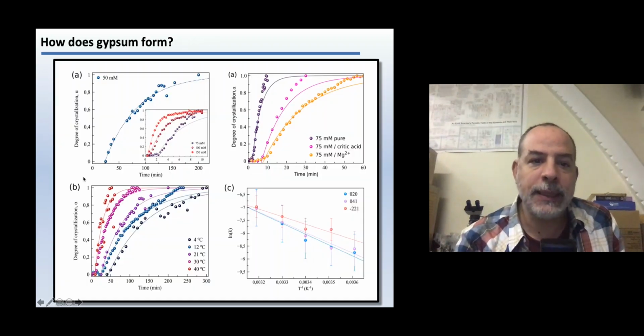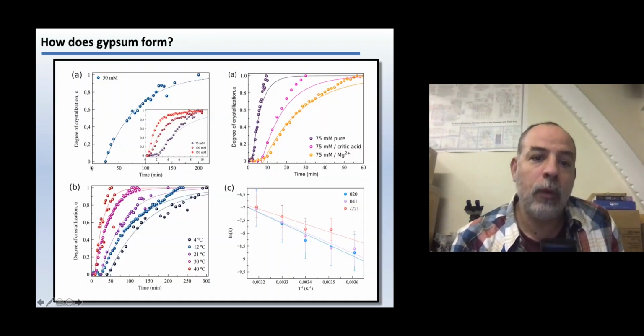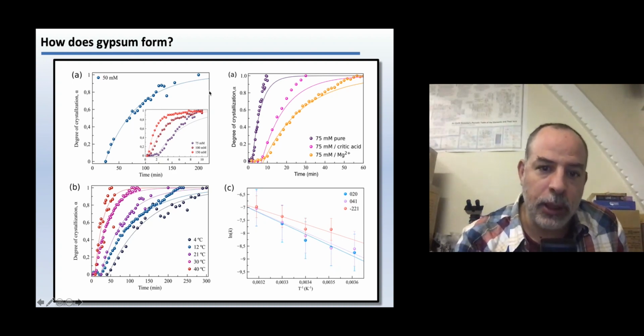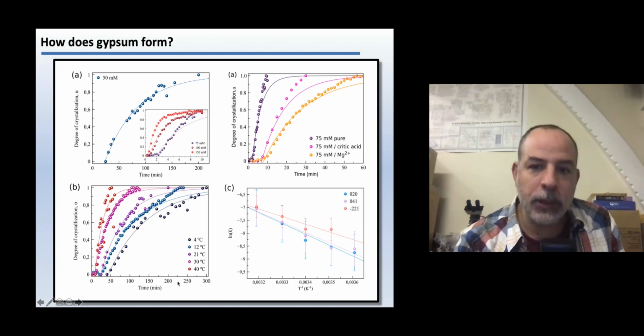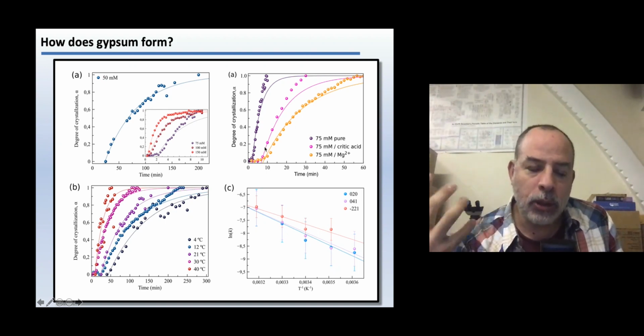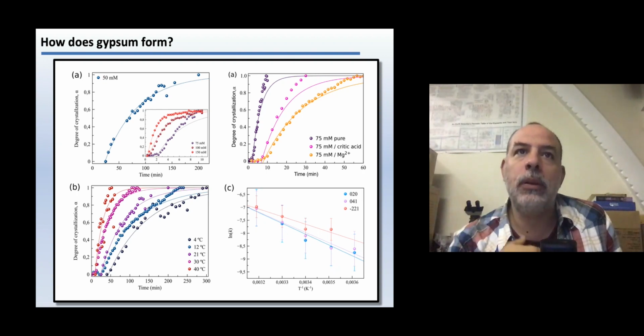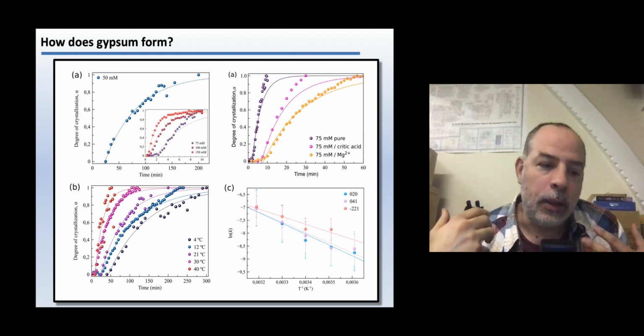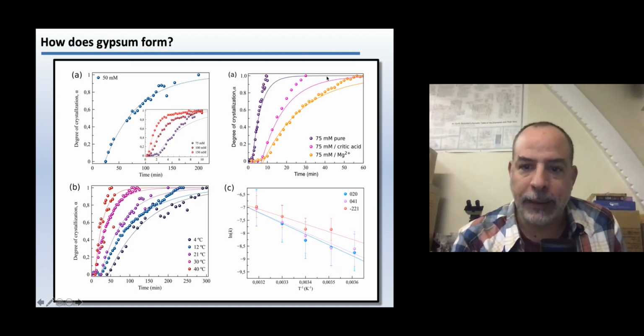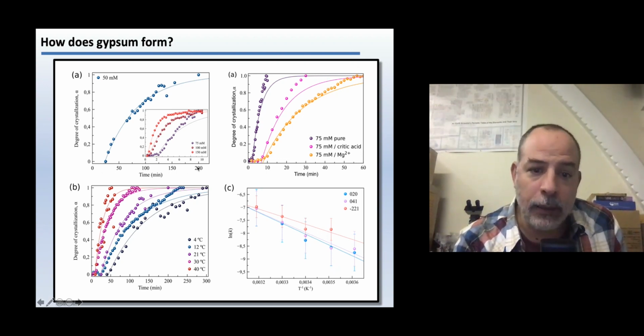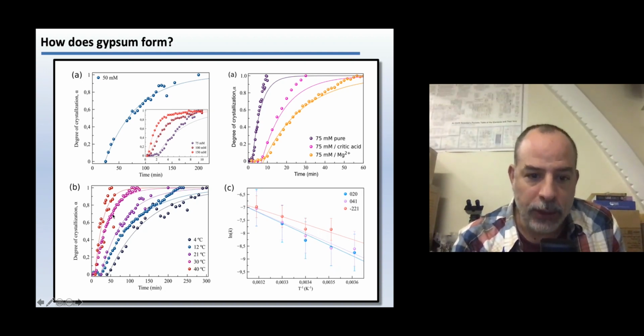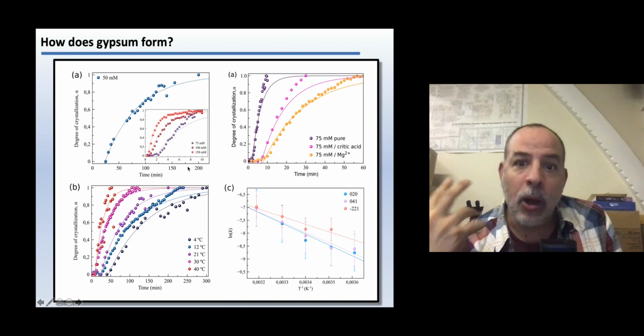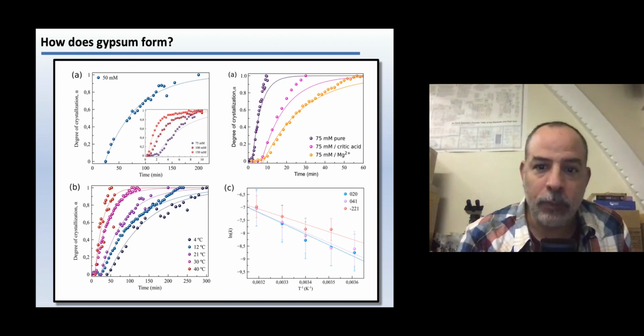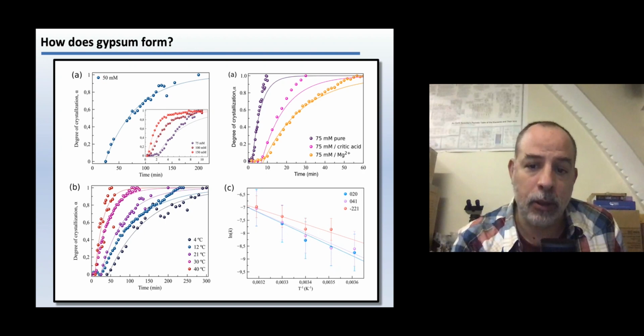So when we follow this by using synchrotron-based techniques, we could follow these reactions using different concentrations of calcium sulfate at different temperatures, also using organics and inorganics, to try to see if it was possible to delay or to slow down the growth of bassanite, which is something that happened. But as you can see here in time, things happen in less than a couple of hours. So this crystallization process is very fast, and we can only follow this by using synchrotron-based techniques. Otherwise, it will be very, very complicated.